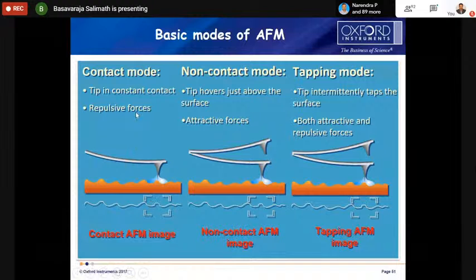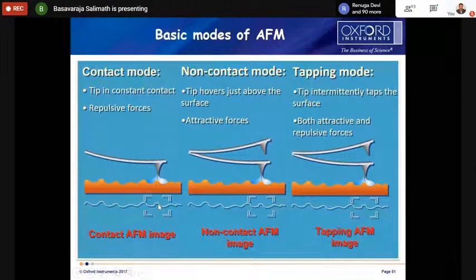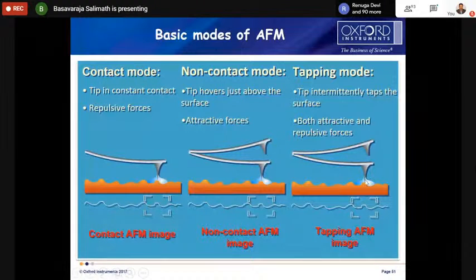Contact mode works in the repulsive force region, and as it is touching the sample, if there is a small water layer on the sample, since we do AFM in ambient conditions, sometimes because of humidity a very small amount of water layer may be there. But in contact mode, the tip goes inside this water layer and scans the surface, so you get the correct surface morphology. In the case of tapping mode also, it is oscillating and tapping the surface, so it also goes inside the water layer and gives us the correct image.